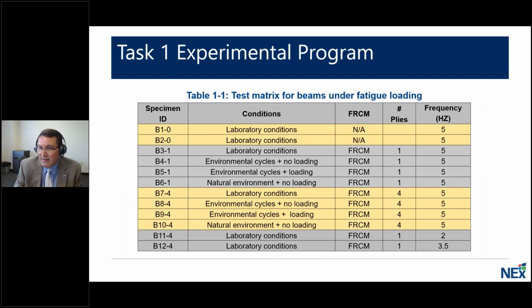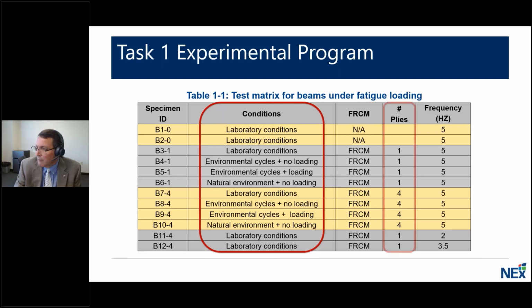that we looked at. This table shows our test matrix, and the variables included the environmental cycles with and without stress, external natural exposure, number of plies. We also looked at the frequency of the fatigue testing. I want to mention, as you see in this plot, we looked at 1 and 4 plies. It may be noted that a collaborating institution, the University of Miami and Antonio Nanni's group, complemented what we were doing by examining 2 and 3 plies concurrently when this research was done in the laboratory. So we went 1 through 4. Our testing focused on 1 and 4 plies.